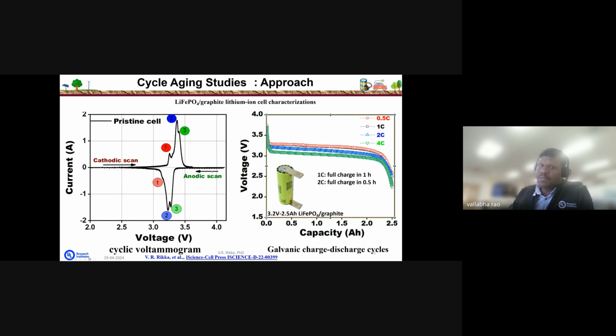This helps us implement our test conditions, because whenever we are operating at different or higher charge currents, from low charge current to high charge current, the voltage will always drop. For example, if the discharge cutoff voltage is around 2.8 volts and you operate this cell at a higher C rate while maintaining the same limiting test condition, the obtained capacity will be lesser than that of the lower C rate test conditions.